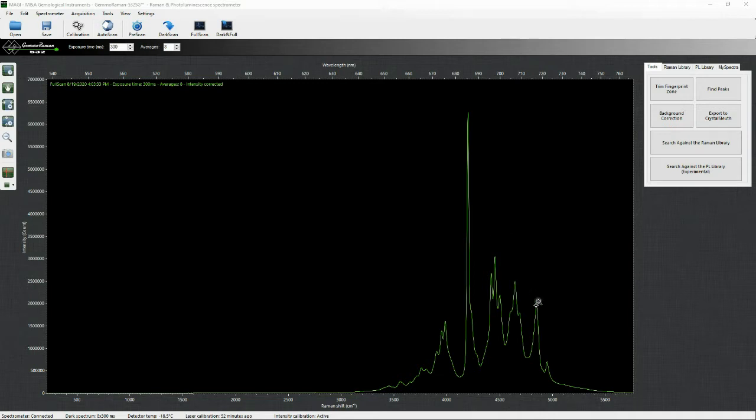This happens because the stone contains elements which trigger photoluminescence reactions once exposed to the laser beam. This emission can sometimes be strong enough to make a Raman signal impossible to be detected by the spectrometer. Chromium is the most notable example of an element causing a strong PL reaction.